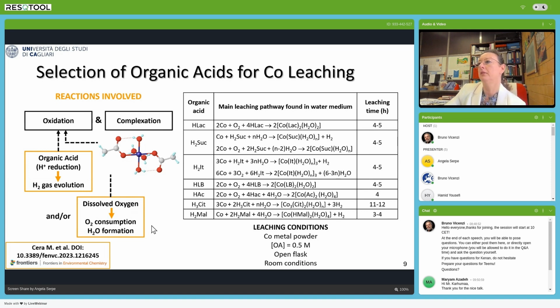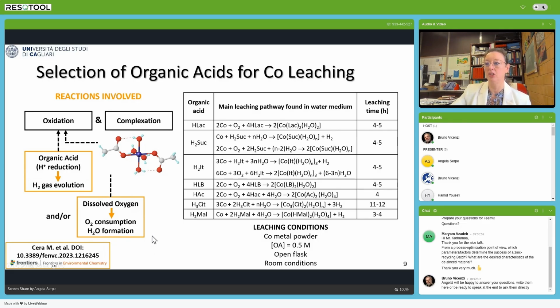Through this kind of study, we were able to define two main classes of organic acids, because in the metal leaching from, for example, tungsten carbide cobalt alloys, for making cobalt go into solution, we need an oxidizing leaching. So we need the oxidation of cobalt to cobalt 2+, and the formation of a soluble species that can be dissolved in the solvent of the leaching.